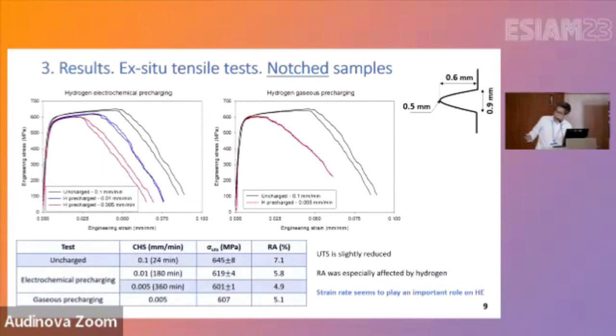Regarding the notch tensile samples, they were tested after the electrochemical and after the gaseous precharging at high pressure hydrogen gas. Based on these results, we can see in this case that ultimate tensile strength was slightly reduced by the effect of the hydrogen atoms. Reduction of area was especially affected by hydrogen.